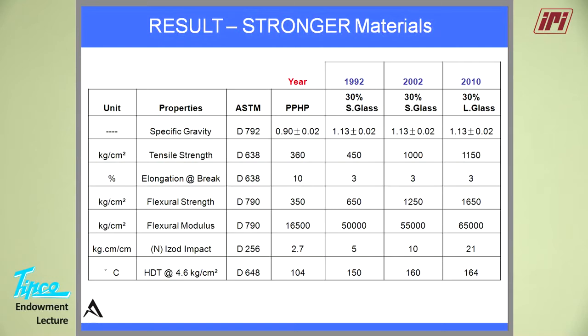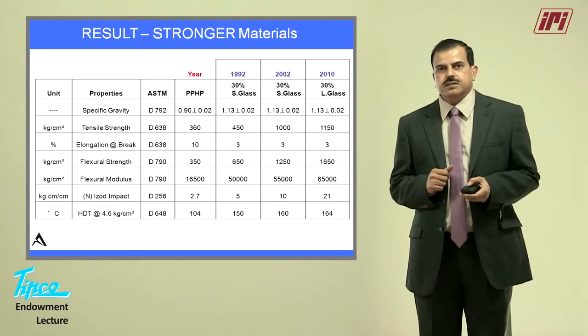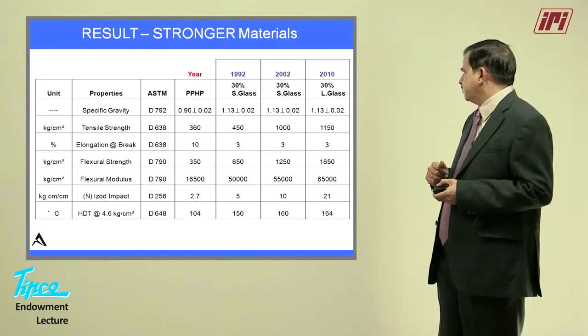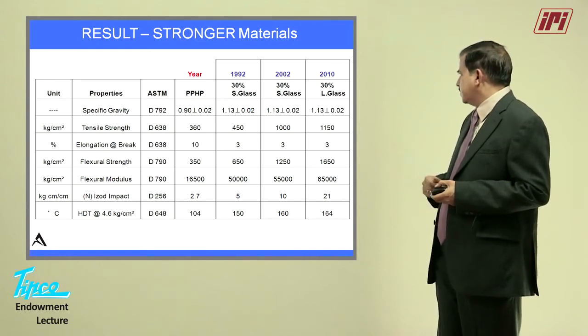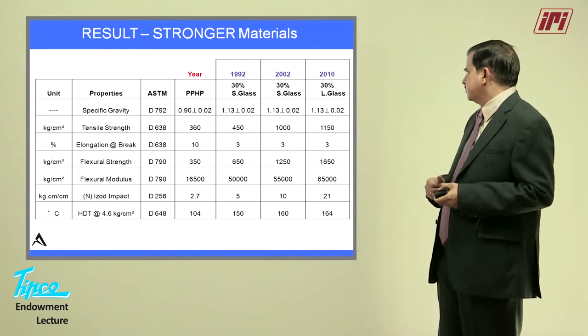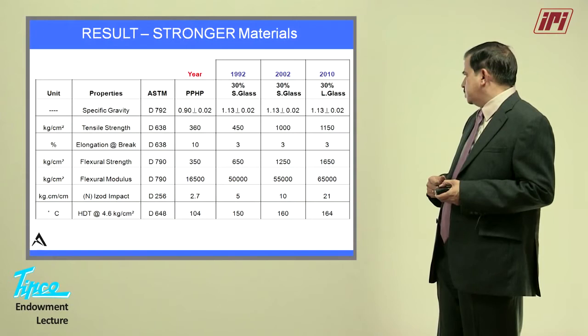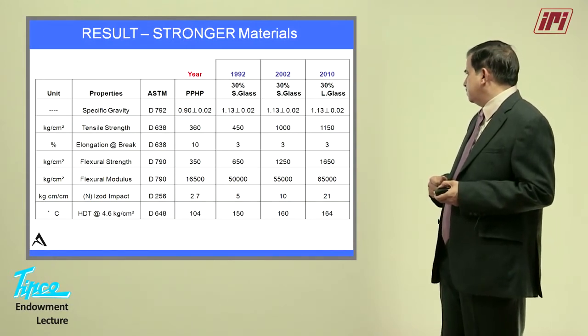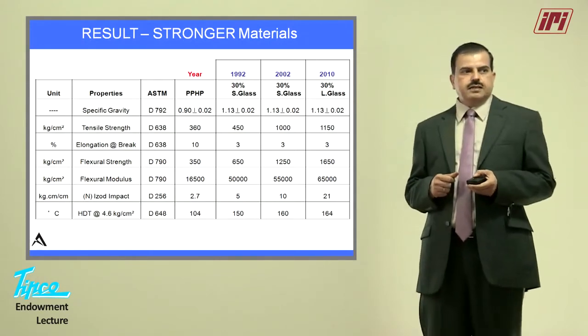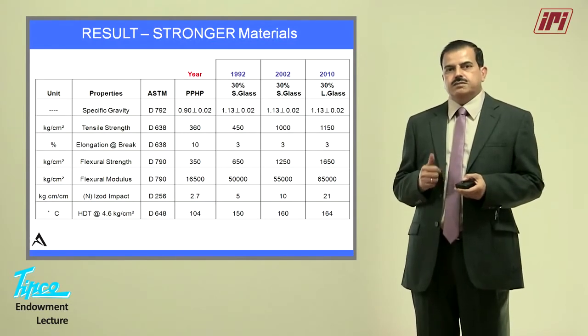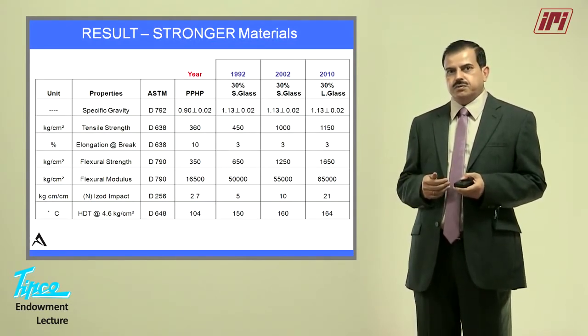Especially you keep your eyes on impact strength. I will say that in 1992 glass fiber PP 30% was having 5 impact. In 2002 it was improved to 10, and in 2010 it has become 21. So a long way, approximately 4 times impact strength you get in today's long glass fiber PP compounds versus 20 years back short glass fiber PP compound with the same loading of glass. As you can see, tensile also has improved almost 2.5 times, and flexural also has improved by almost 30%. So these are the advantages: you have achieved much higher impact strength, and tensile strength has improved. Flexural also has been improved a little bit.